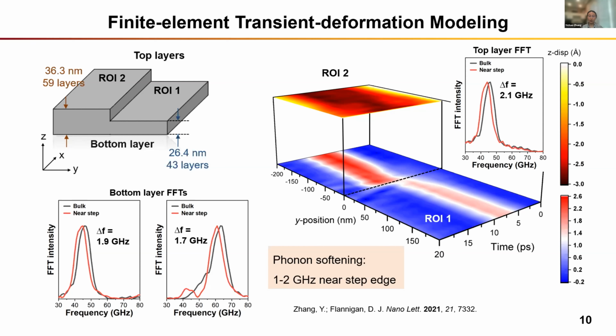The FFT profiles near the step edge, which are the red profiles, do show about 1 to 2 gigahertz of reduction, which agrees with the experimental results quite well. And the simulation results really confirm our hypothesis that the incoherent atomic displacement at the step edge leads to the softening of the phonon.